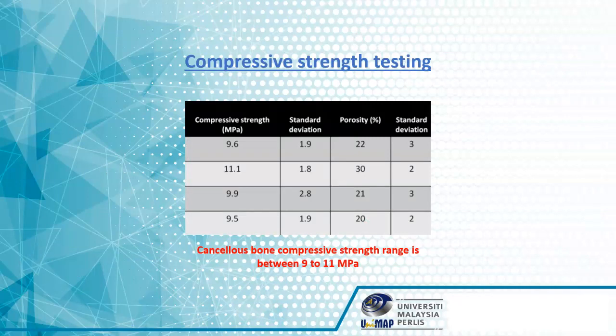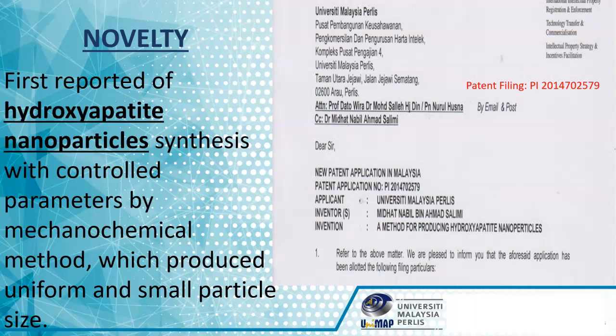In terms of compressive strength testing, it was shown that the bone compressive strength range is between 9 to 11 megapascal, which is very good to be used as an artificial bone application, which is very similar to natural bone compressive strength. In terms of novelty, this is the first reported hydroxyapatite nanoparticle synthesis with control parameters by mechanochemical method, which produces uniform and small particle size.